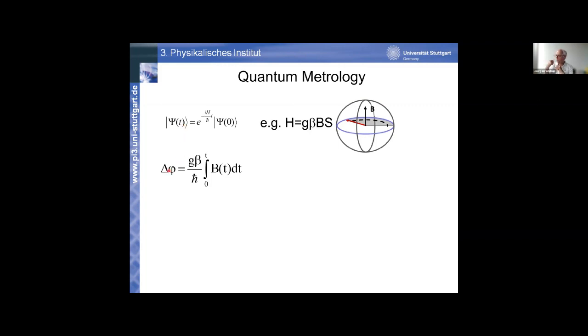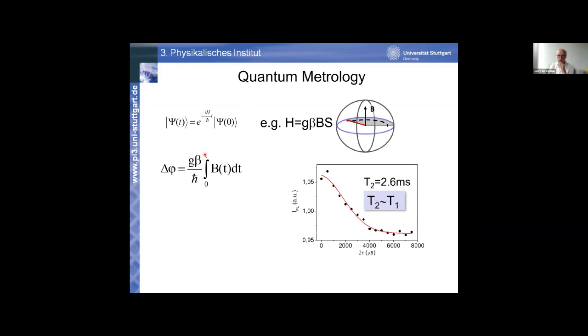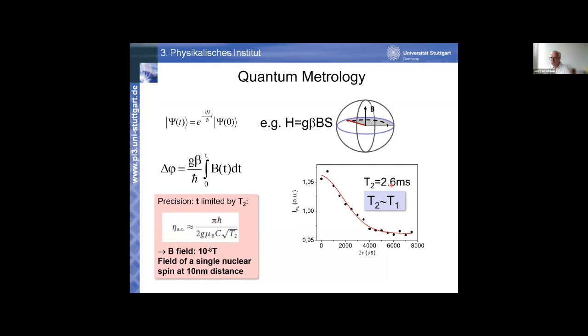And what we measure is the phase the spin has acquired over the measurement time small t. The maximum time we can use to measure phi with largest precision, at least in an experiment where we have no entanglement, no correlation whatsoever, is given by the spin dephasing time, which is on the order of 3 milliseconds or so. And then you can plug this into your sensitivity equation, which once again is rather universal throughout different types of sensors. Then this is what you get.